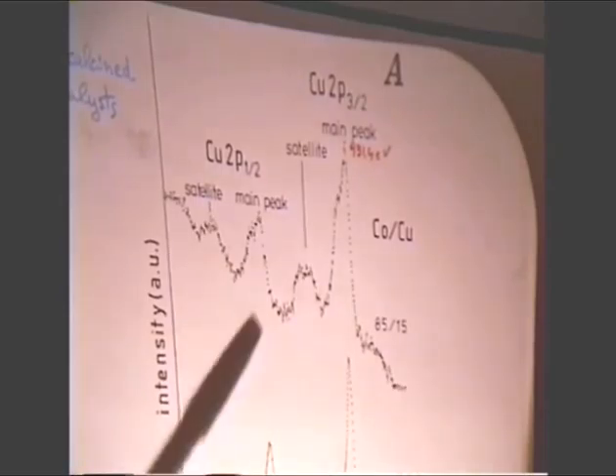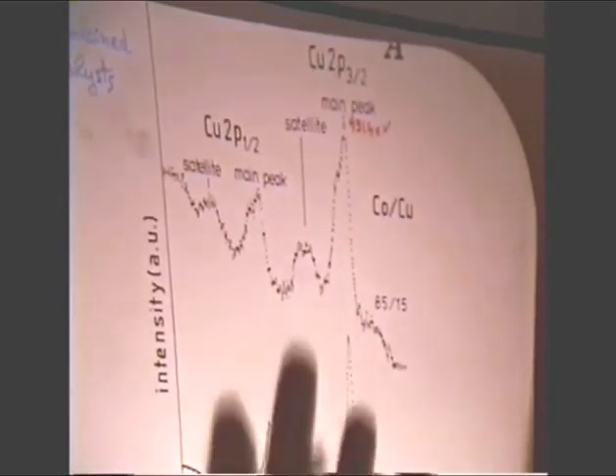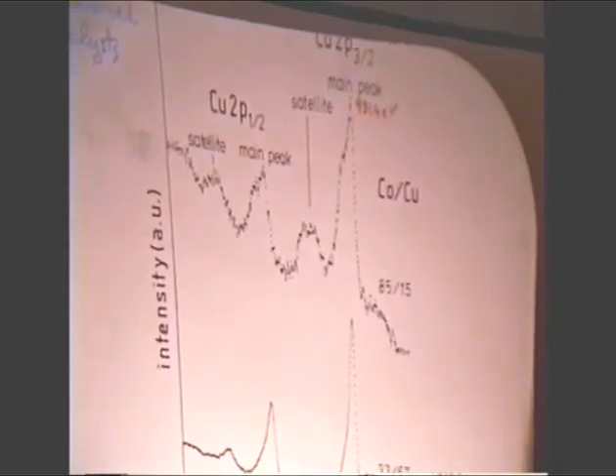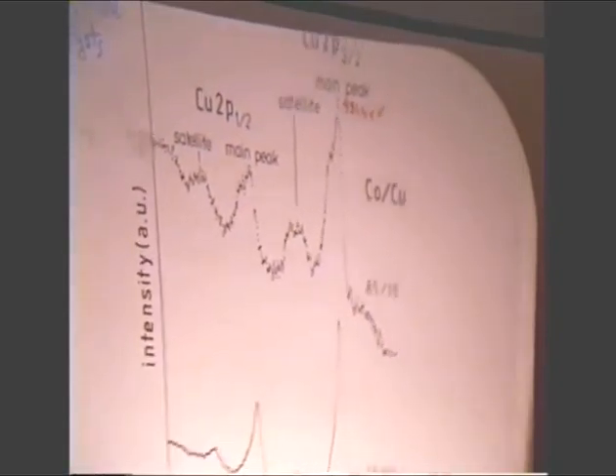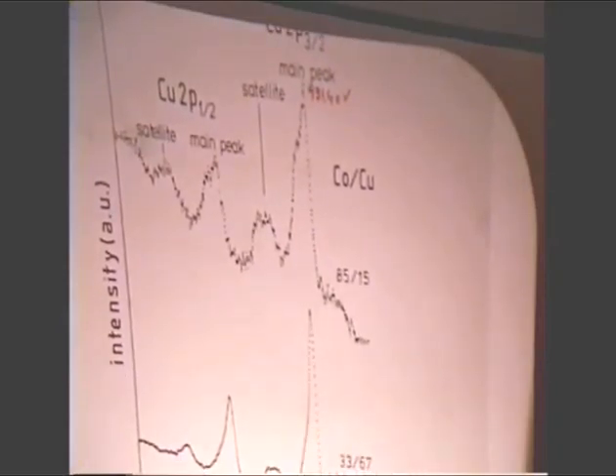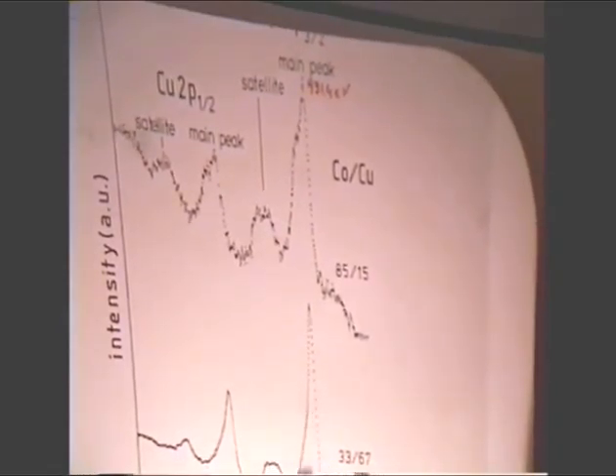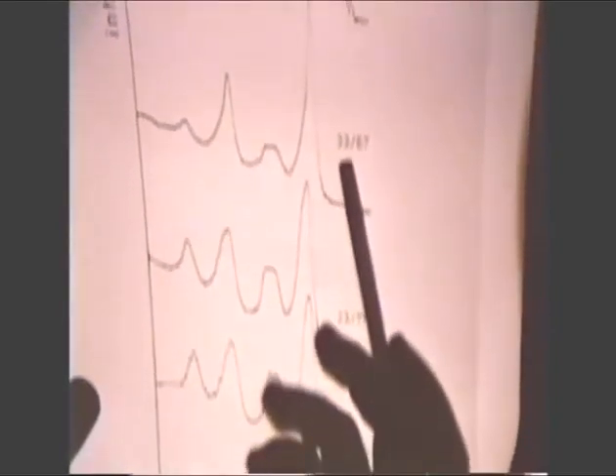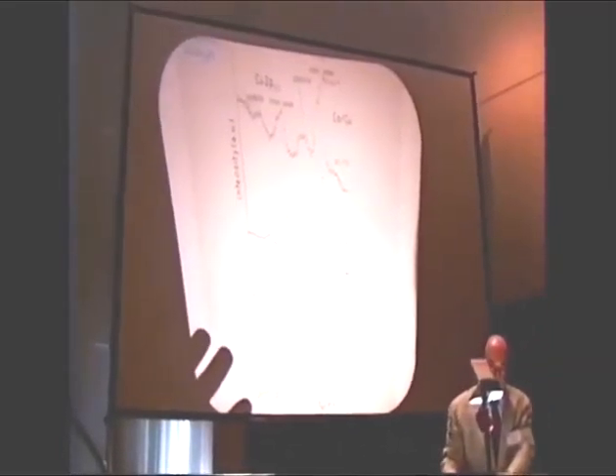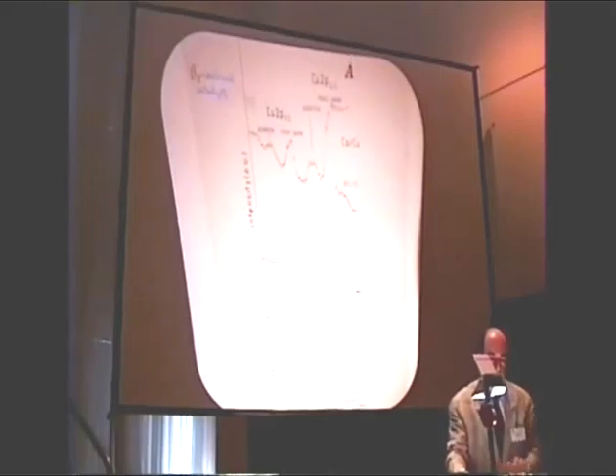And I will show this particular aspect later. As the amount of copper increased, we observed that the main peak became more asymmetric for the 33-67 composition. And then we also still have a component for the other catalysts. So XPS also confirmed that at the surface of the Co/Cu catalyst, we have the presence of both the copper 1 plus and the copper 2 plus species.